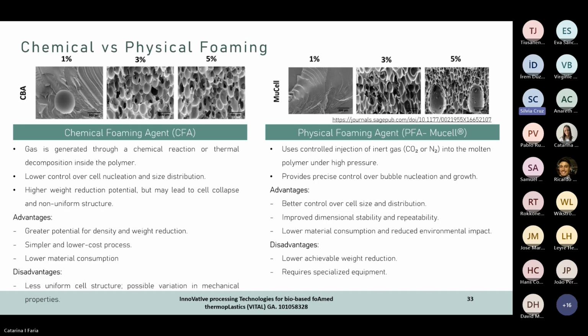For both variants, it is important that the shut-off nozzle should be considered in order to prevent the foaming and the return of the material into the barrel.